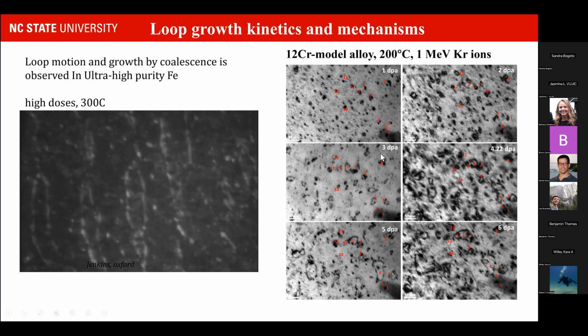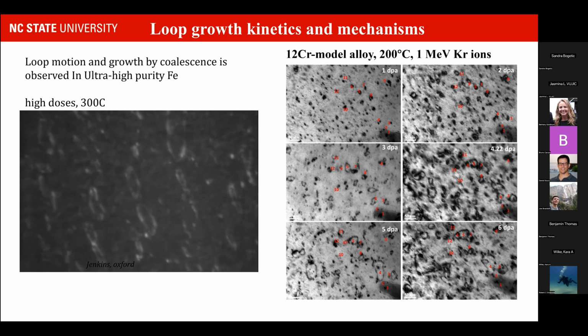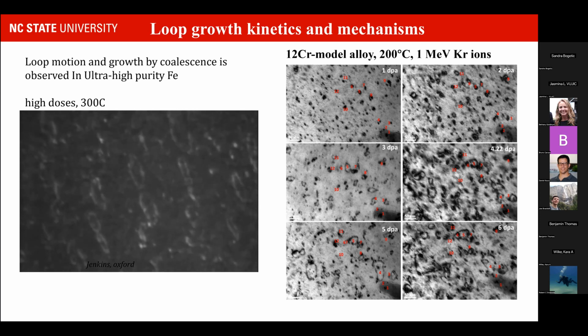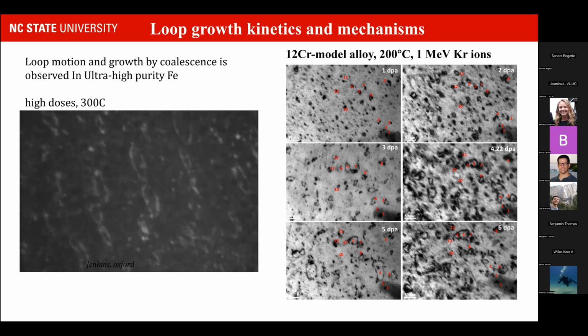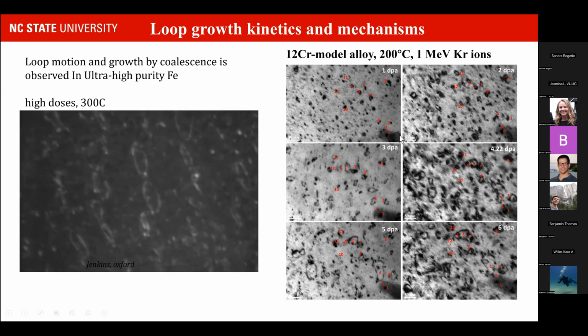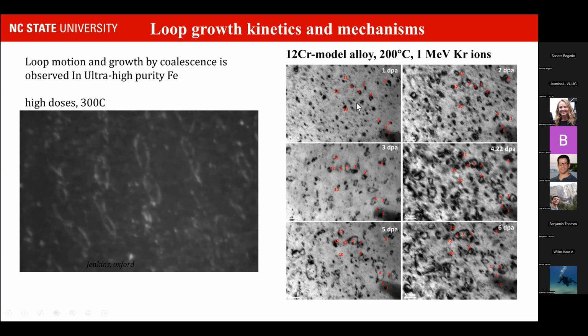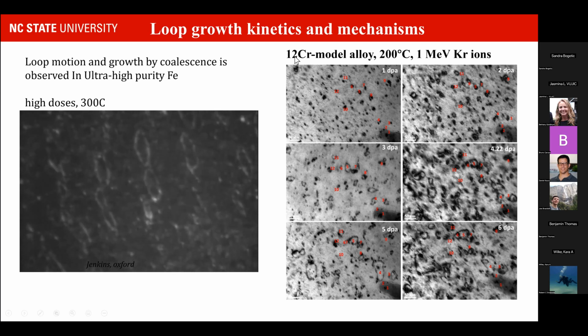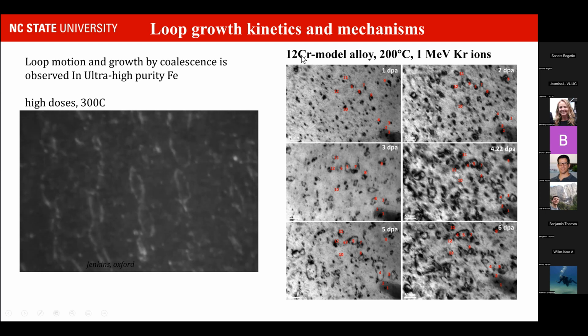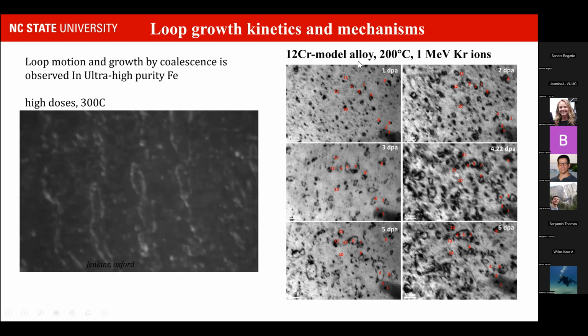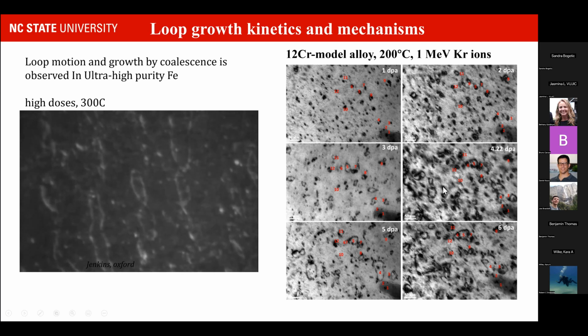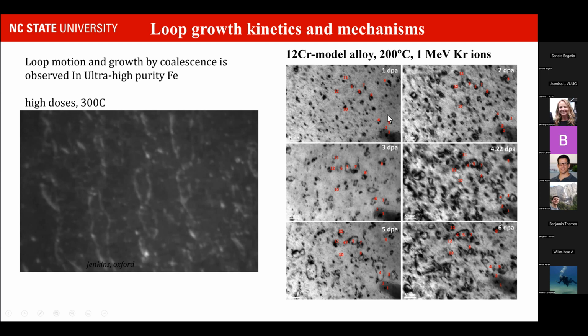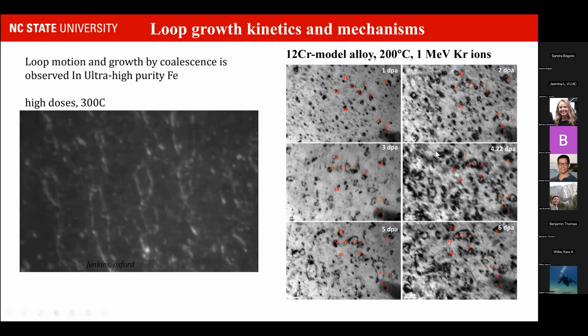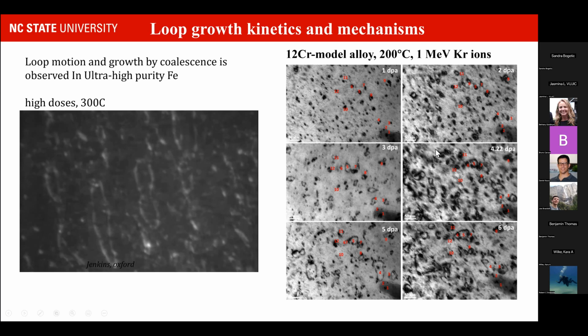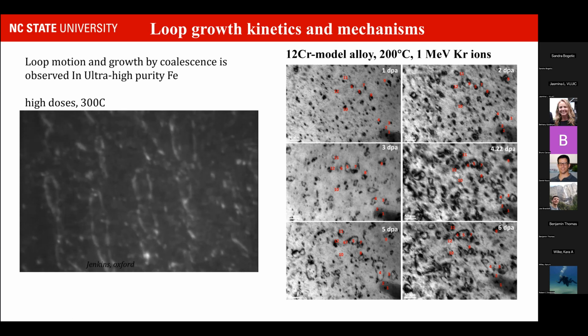The question is, does it happen also when we are dealing with a binary alloy or with an actual commercial alloy? For that matter, we had done very similar experiments, but using iron, to which 12% of chromium were added and a little bit of carbon to make it a steel. And doing the similar experiments, we observed very different results. The motion, the mobility of the loops is extremely reduced. In fact, they're not moving much at all.